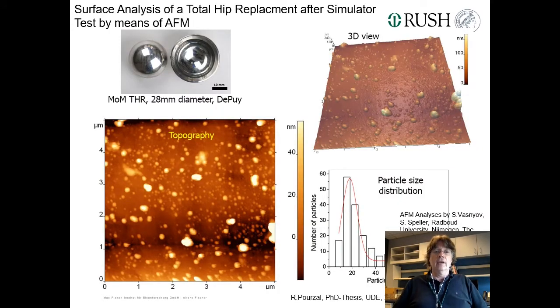If you then analyze the surface, for instance, by AFM, which in this case has been done by Sergei Vasnyov, in Sylvia Speller's group when she was still at the Radboud University in Nijmegen in the Netherlands. You see, these are remains of the lubricant, in this particular case denatured proteins and wear particles, which partly agglomerate outside of the contact. In contact, we think they stay as small as you would normally find them here, and then you can do some measurements and find that these particles have a nanometer size, so most of them are below 100 nanometer.